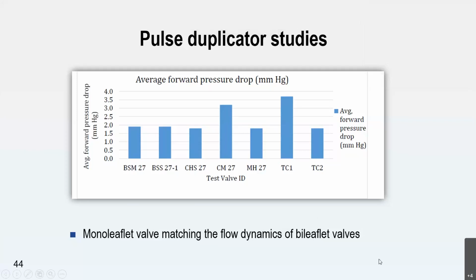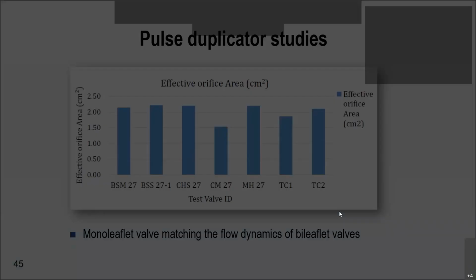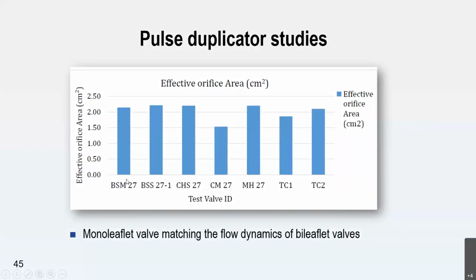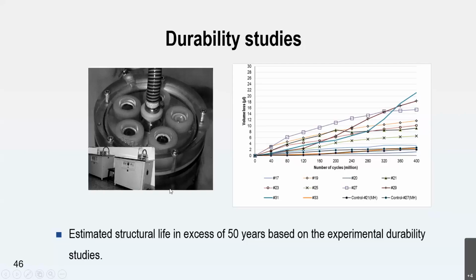Then the pulse duplicator studies also showed that the average pressure drops are the lowest among the different valves available in the market, like the VSS, Carbomedics, Medtronic, and all the popular brands in the market. It was matching or marginally less than many of the devices. Even the effective orifice area, which is again a measure of the gradient, was also found to be good, comparable to the other devices. Then the durability was studied, and based on the durability studies for more than 400 million cycles, we estimated that the structural life of the device will be 50 years or better.